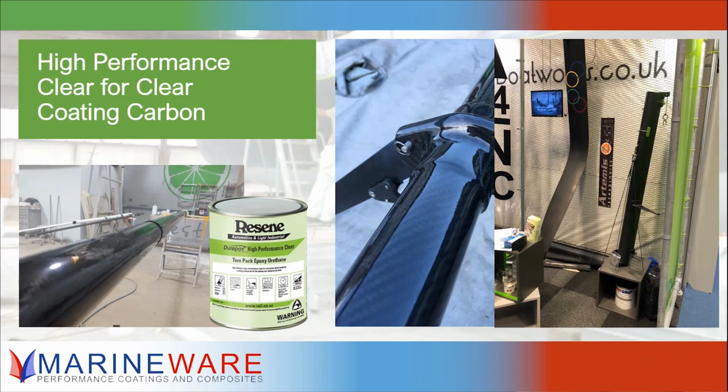So yeah, we do the Exocet Moth decks with high performance clear as well, and again just brush a few coats on to do the pinhole filling, and then a final coat over the top. Yeah. I like to use the brushing and rolling trick as well to help with those pinholes. Sometimes I'll brush and roll it and then almost spray a coat straight over the top as fast as I can. So you try and get slightly the finish of spraying, but the ability to push paint into pinholes with the roller works quite nicely.